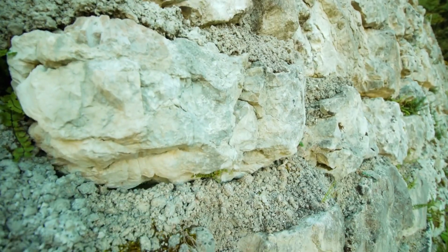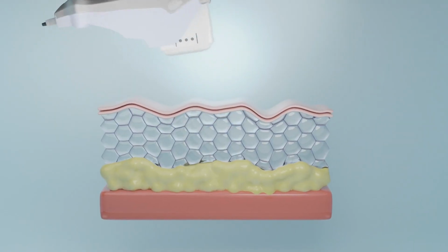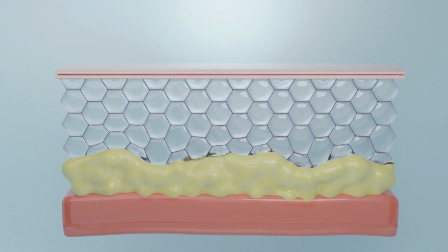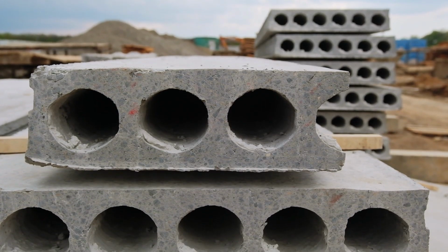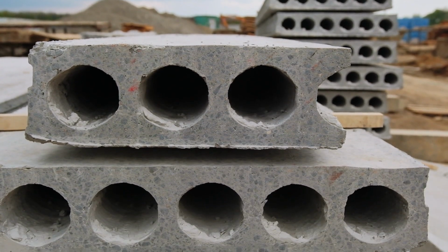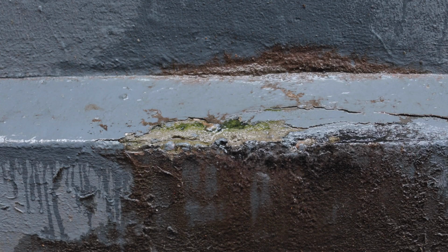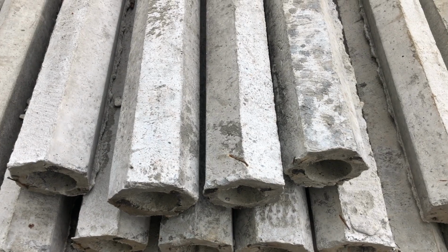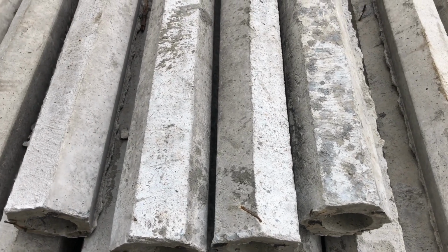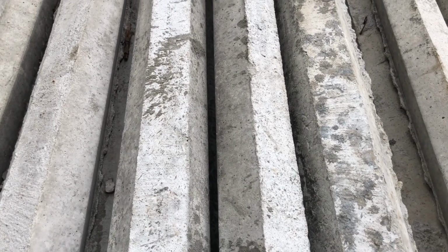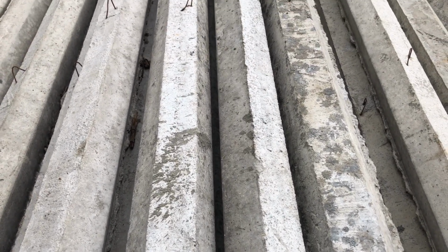Now look at how Romans cast. They favored massive, low-water mixes rammed into formwork around large stone aggregate. Low water means fewer connected pores after hardening. Coarse aggregate provides a skeleton that limits shrinkage and spreads stress. Because there's no embedded steel in these giant blocks and domes, there's no hidden corrosion engine to blow apart the cover concrete from within. Modern reinforced concrete, by contrast, solves tension with steel but creates a new vulnerability.